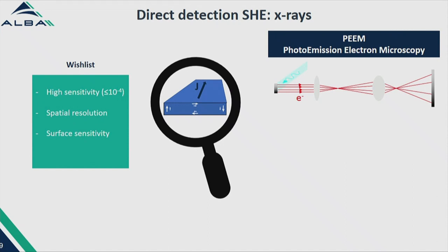So we have a very high surface sensitivity because we detect only the electrons produced near the surface, of the order of 2, 3, 4, 5 nanometers. So of course, we can make an experiment where we detect this signal, but not this one, okay? And like this, we have a larger detecting surface and we don't have to look at a very thin stripe close to the edges, but can look at a fairly large surface. This is one possible advantage.